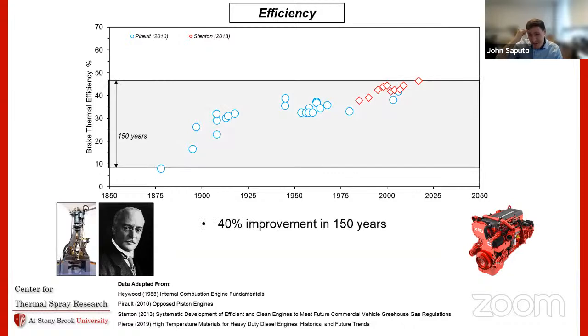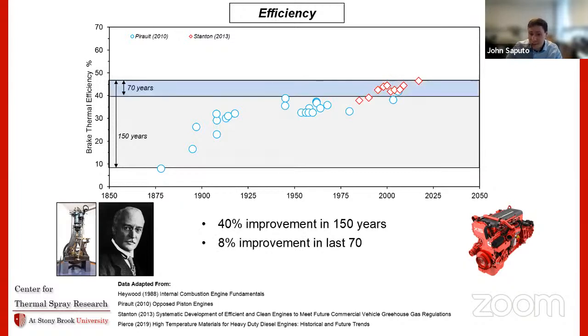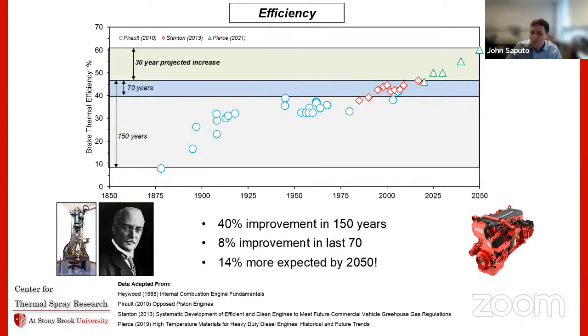So it's interesting, you get about a 40% improvement over the span of about 150 years. Over the past 70 years, you only see an 8% improvement. So that's kind of interesting. Things saturate after about 50 years of improvement and have gone really slowly since then. So if you look at this in the future, what do people expect to happen? There's projections that in the next 30 years or so, you'll see about a 14% improvement in efficiency in these systems. So considering that there's only been 8% in the past 70 years, 14% seems like a suspicious number.